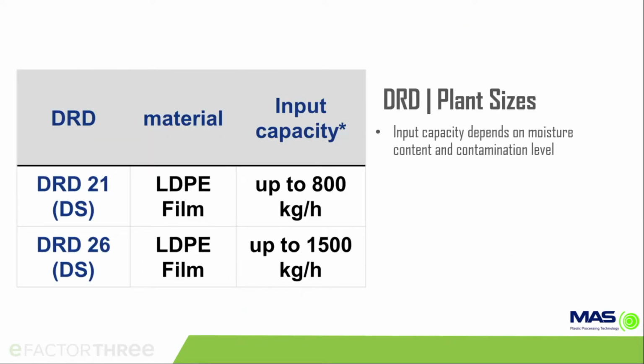And these units come in two different sizes, and it's always measured in input capacity. If we're looking at the larger unit at 1,500 kilograms input, 3,300 pounds, you have to deduct probably 50% of what you're putting in, which will come out as cleaned material. Now the good thing is you have no water treatment. You get a dry mass that you can dispose of. And it's a very simple process.